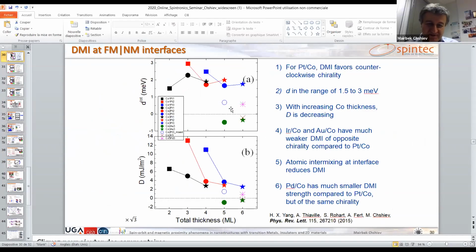We have ideal interfaces, except that our experimental colleagues were not happy with the ideal interfaces in the calculations. So we were simply swapping atoms, and in some sense you still cannot call it an appropriate disorder calculation, obviously. But when you swap, you mix your cobalt and platinum in some places at your interface, and we calculated the DMI. And this is the point for cobalt platinum. When you start to swap cobalt and platinum atoms at the interface, the impact is that you strongly reduce your DMI. You see?